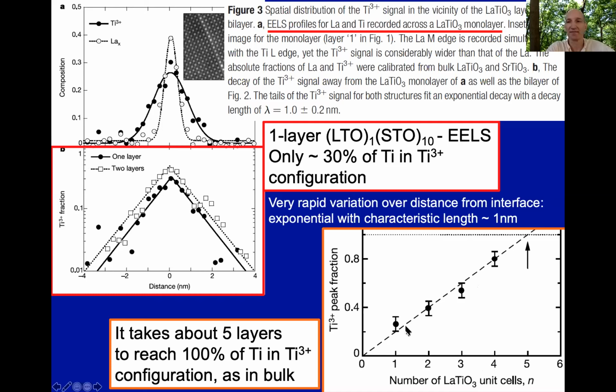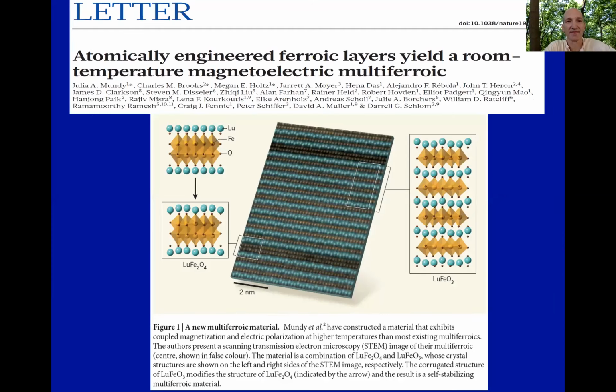While if we increase the number of layers to about 5 layers of LTO, we get almost 100% titanium 3+, and we are back to the bulk behavior, which is a Mott insulator with a moderate gap. So this is a simple example, but a beautiful design example of how you can actually engineer metallicity by charge transfer between two insulators in the bulk. And there are some much more sophisticated and complex examples of similar phenomena with different functionalities.